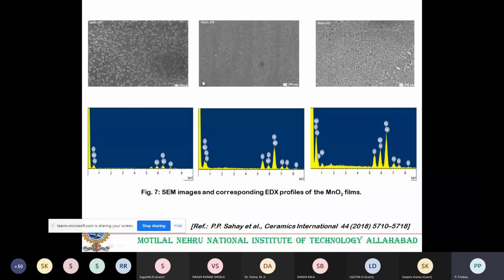if you study the AFM, when you perform the AFM and analyze the data, there is a projected area and there is the image surface area. So if the image surface area is more, in that case, what will happen? The electrolyte will come in more area. So the redox reaction will occur in a larger area compared to the film which has less roughness.